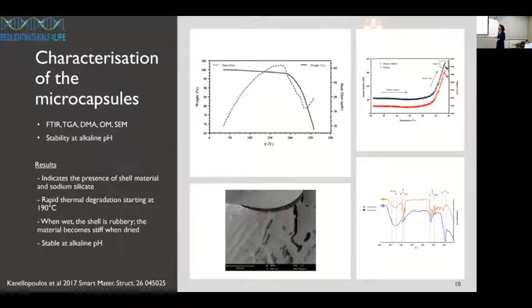One important property of these capsules is that when they are wet, they are very rubbery, as gelatin is when we're playing with it. But when they are dry, they're very, very brittle, like those gelatin sheets you buy in the supermarket. That's very precious when we're talking about self-healing, because you want the capsules to survive the mixing because they are rubbery. But then when they dry out, they are very brittle, and the crack is going to easily trigger the microcapsules. And FTIR for characterization of these capsules as well.